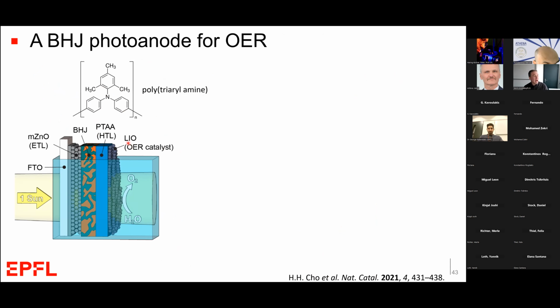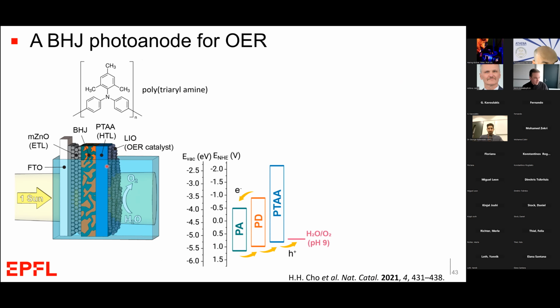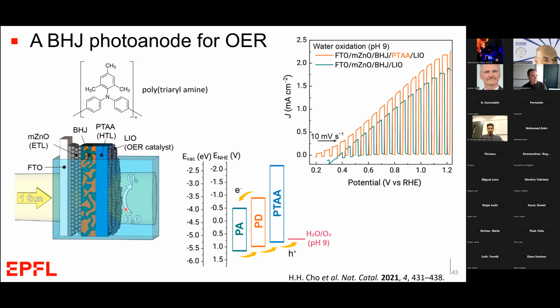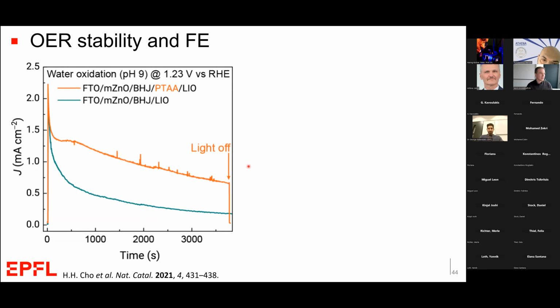Finally, by applying a lithium-doped iridium oxide OER catalyst, we were able to demonstrate overall water oxidation reaction occurring under illumination in these photoanodes. The effect of the PTAA is shown here on the ability to shift the LSV curve a little bit in the cathodic direction, giving us more potential. But it's more importantly shown here where we achieve better stability, especially in the initial operation of this photoanode.